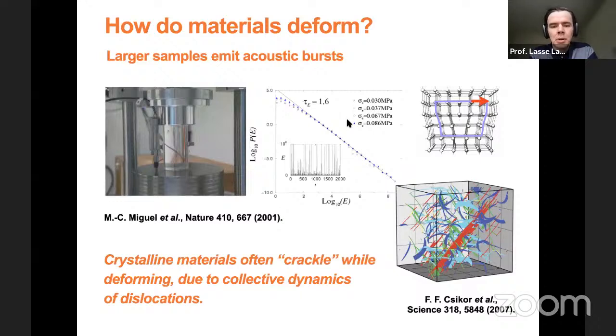And these originate from some collective dynamics of dislocations in the crystal, because plastic deformation, of course, is a process that is mediated by the stress-driven motion of these dislocations, which are topological line-like defects that live in your crystal.